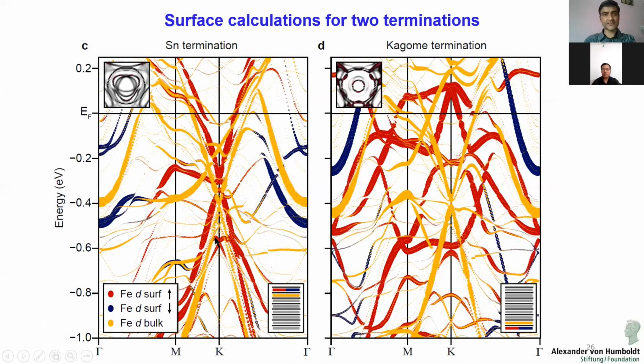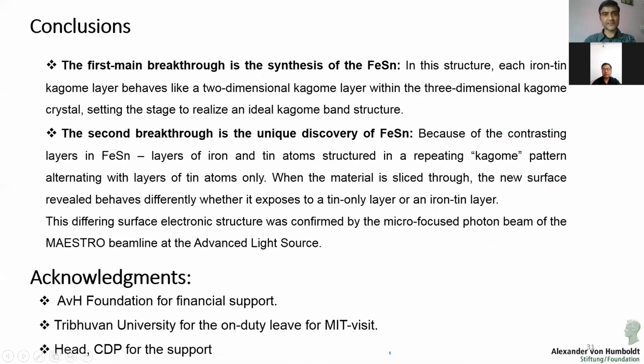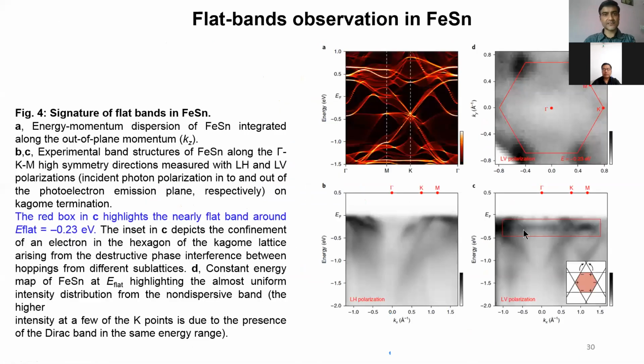From this, the first main breakthrough is the synthesis of this particular material as a single crystal and then exploring the surface state. The second breakthrough was the unique properties that it gives rise to, which are a flat band and Dirac cone-like features. Well, I forgot to mention the flat band which was lying here. Let me show you where we find the flat band. This is the Fermi level, and just below that you can see that under LV polarization only, we can observe the flatness of the band. Based on that, we consider the DFT calculation as well.